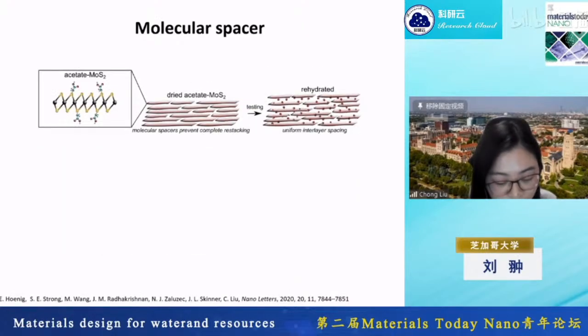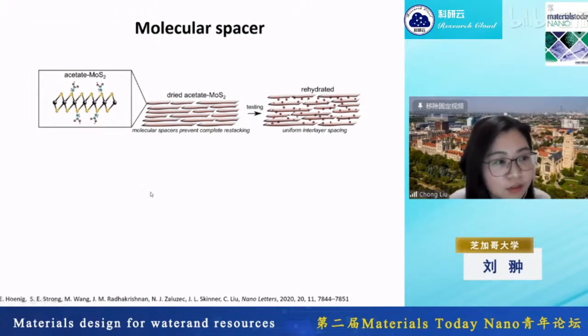So this tells you that pristine molysulfide is actually not a good or suitable material for you to work with for membranes. The solution we thought about in this case is to put a permanent spacer on top of the surface of the molysulfide. This way you can not only solve the issue of restacking, but it also provides you a tuning knob to tune the surface chemistry. Then you can really study how the surface chemistry affects the transport of water and ions.